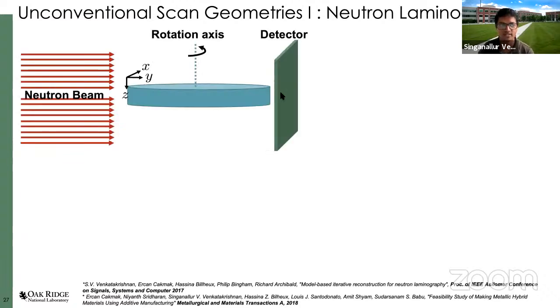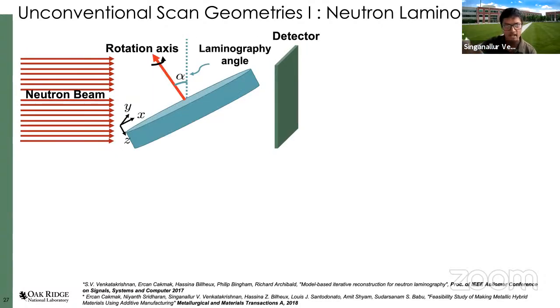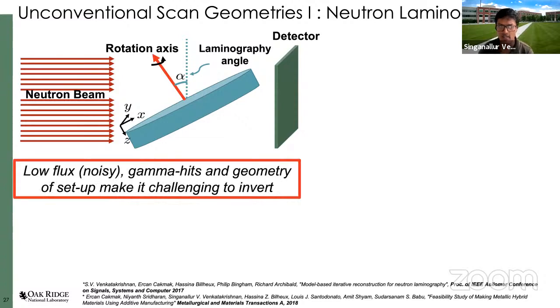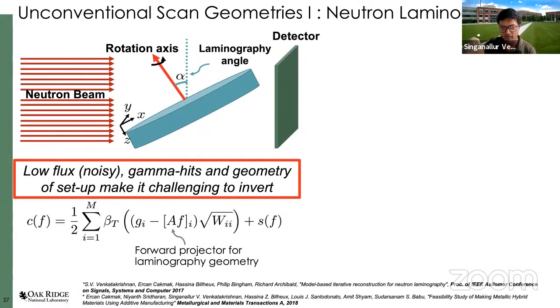So one example is called neutron laminography. If you have a very long object and you want to scan it, the neutron beams do not penetrate such an object very well. So scientists are interested in orienting their sample differently. For example, if you can scan, tilt, and then rotate the object, then it's a different technique. This is called laminography. So we've been developing model-based reconstruction methods for such approaches where you have low flux. And in addition, you have the usual challenges in neutrons with low flux, gamma hits, and the geometry. Once you have a complicated geometry, there are no algorithms out there you can just download and use. So we've been developing custom techniques